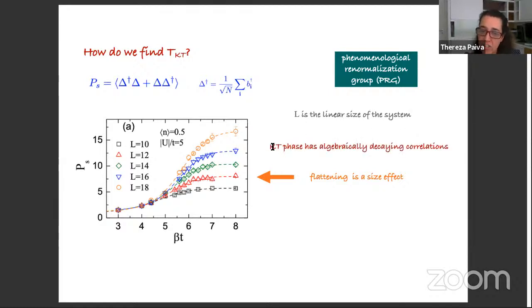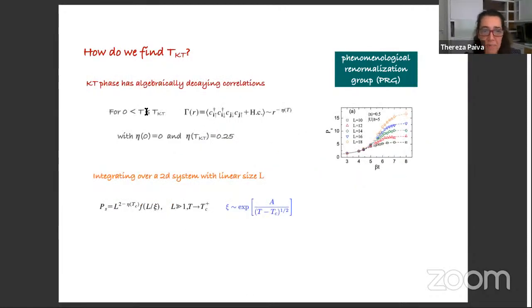And in the Kosterlitz-Thouless phase transition, what we see is that the correlations decay algebraically. So for temperatures between zero and this ordering temperature, the correlations fall off as a power law with exponent minus eta. And this eta is a coefficient that depends on temperature. For zero temperature, it is zero. And at the Kosterlitz-Thouless temperature, it is known to be 1/4.